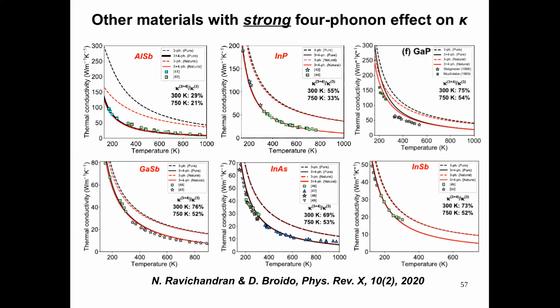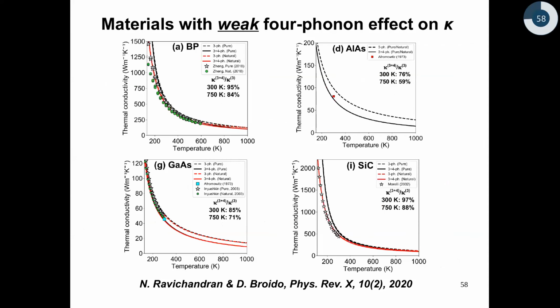And the experiments are really lying on top of the curve without any adjustable parameters. So it's a very predictive scheme, which includes the reality of having higher order effects in thermal transport. But there are also materials where the effect of 4 phonon scattering is weak. So we do find some of the 3-5 compounds like boron phosphide, gallium arsenide, and silicon carbide, where the dashed and the solid lines are roughly overlapping or very close together, indicating that 3 phonon scattering, the conventional picture, is sufficient to describe thermal transport in these materials.